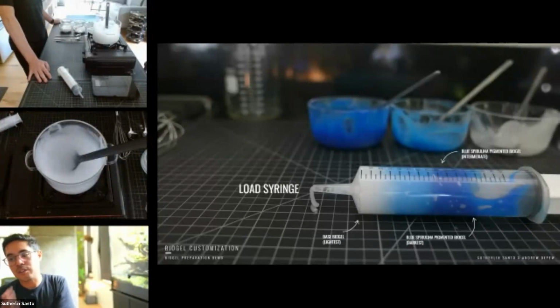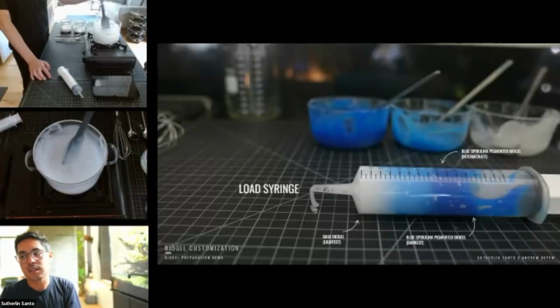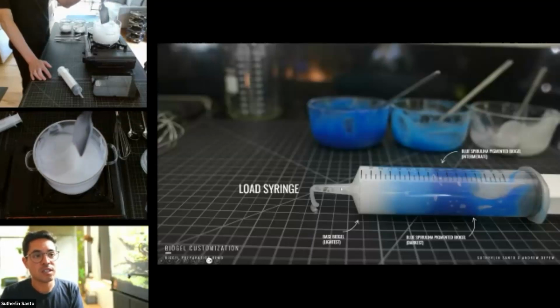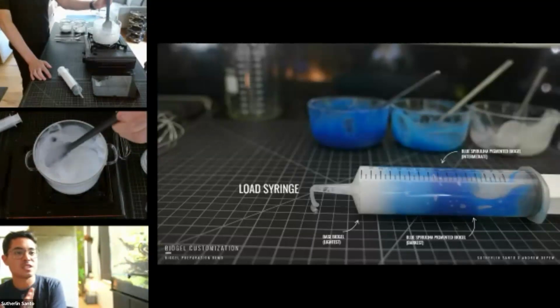It is important to note that in almost all extrusion circumstances, we want the darkest to be last, mostly because no matter what extruder you're using, unless you've got a really high-end extruder with a very reliable auger at the end, some amount of dark material will always get stuck around the nozzle. So if you printed dark blue first, everything you print afterward would have a streak of dark blue. So we always start with our lightest and then end with our darkest.